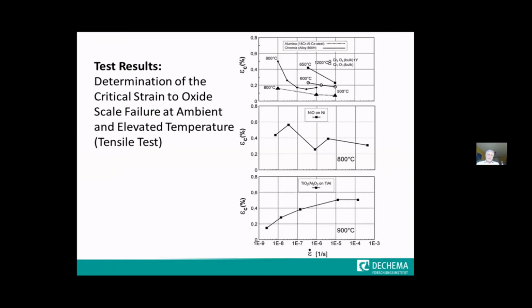In those days, we measured the critical strains for a couple of different oxide scales, for instance, alumina or titania, nickel oxide, chromia, and alumina. And there's one common thing with all these oxide scales, that even at elevated temperatures, 800, 900, and 1,000 degrees C or more, they behave like you would expect it from ceramics. They are brittle. And when you look at the critical strains, they are clearly below 1% of strain. In most cases, it's between 0.2 and 0.6% strain. So this is not a lot.